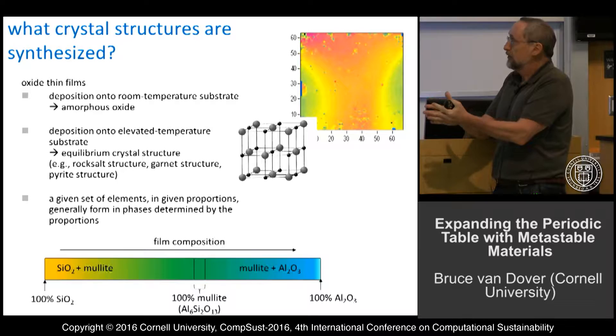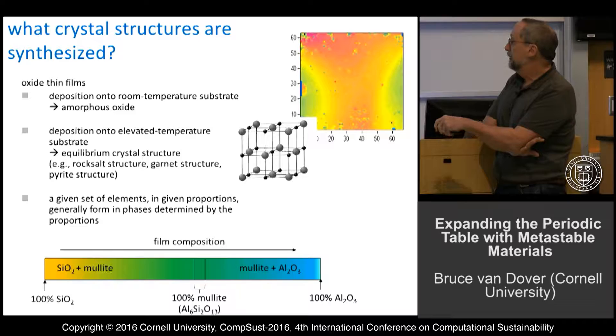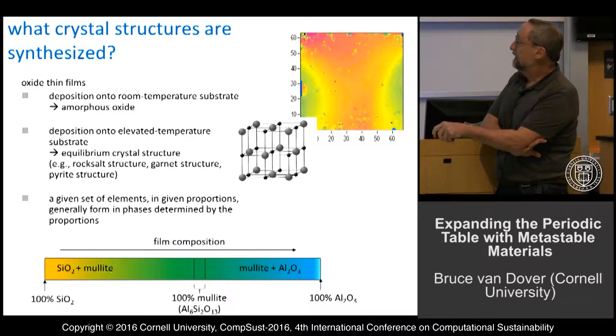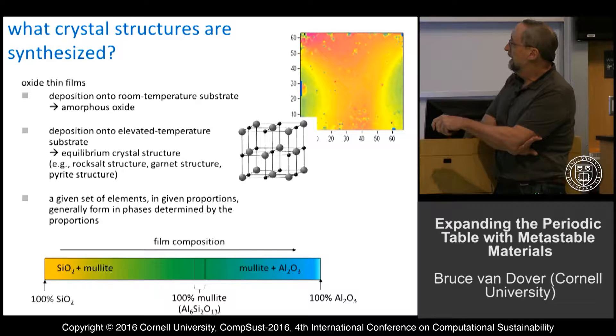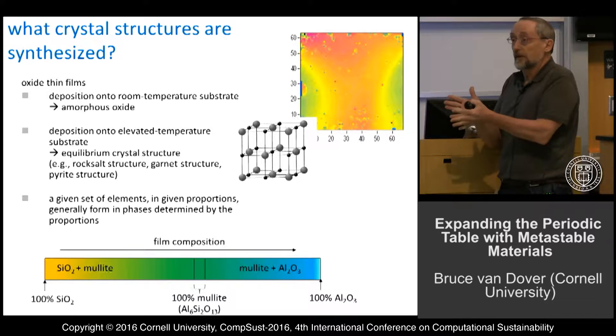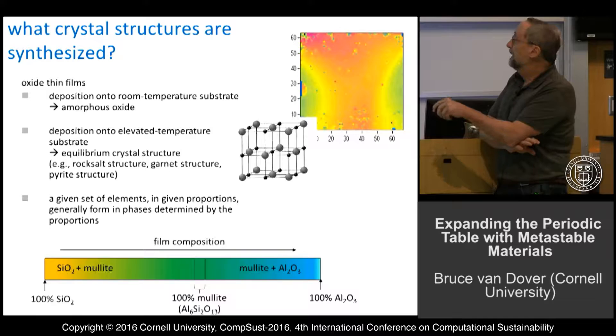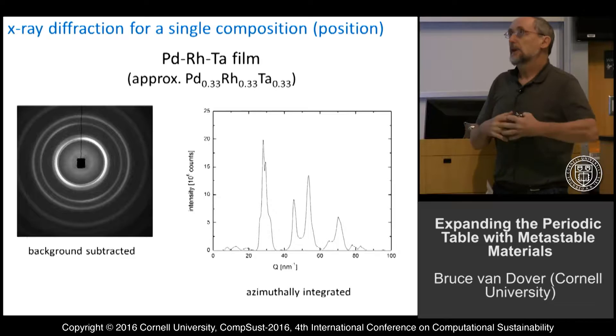For a given set of elements in a particular proportion, they will form phases determined by the proportions of the elements. For example, going from silicon dioxide to aluminum oxide as a function of composition — increasing aluminum concentration from left to right — at one particular composition you get a new compound called mullite. So you have pure SiO₂, pure aluminum oxide, and in between a mixture of mullite plus aluminum oxide in varying ratios. Over one particular region, that's a single-phase region and you get just 100% mullite.